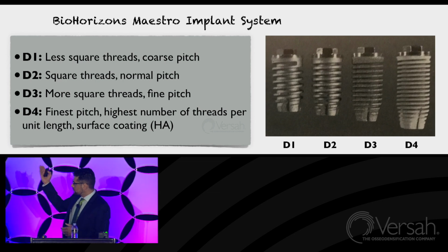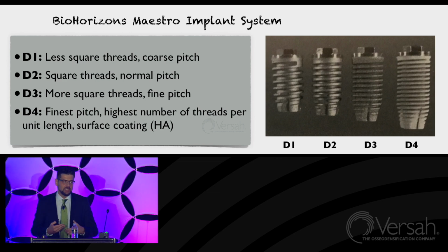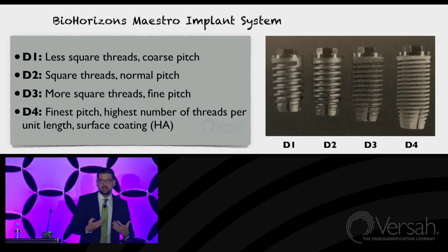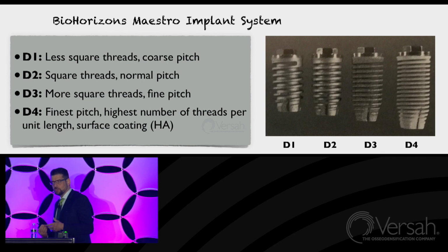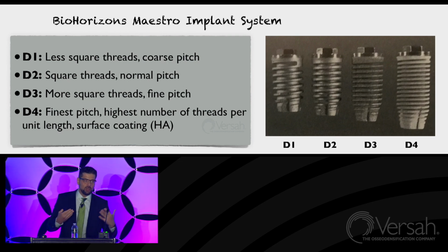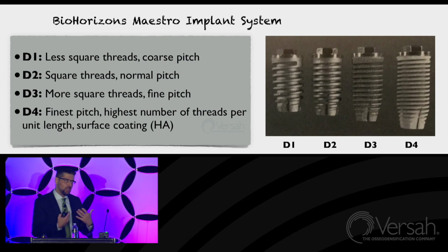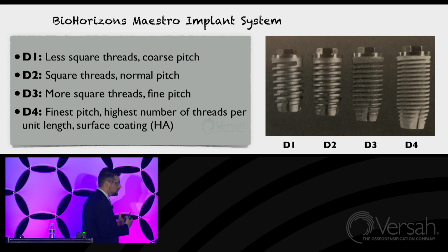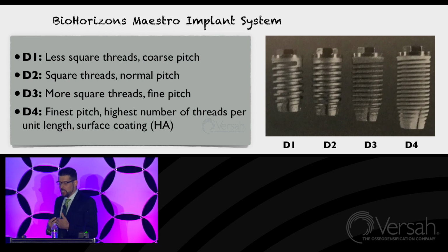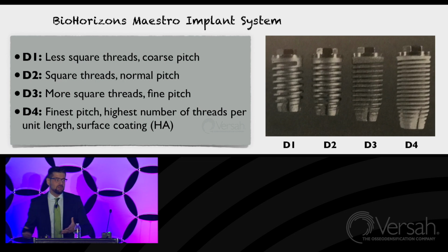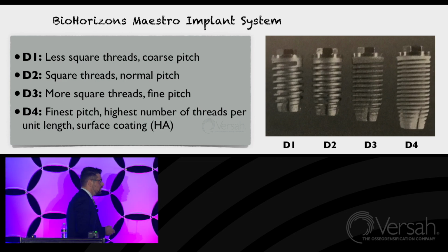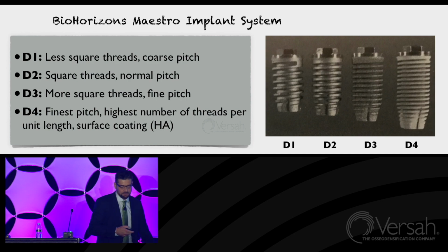Back then, for D4 bone or posterior maxilla, the only solution was to power boost the implant, not only with design, but also with surface coating, which was hydroxyapatite. We all know how successful it was in terms of osseointegration. There's true bonding between the implant and the osseous structure. However, we also learned that that wasn't very stable over time, and that's why these implants are no longer used. But this was a very early attempt.